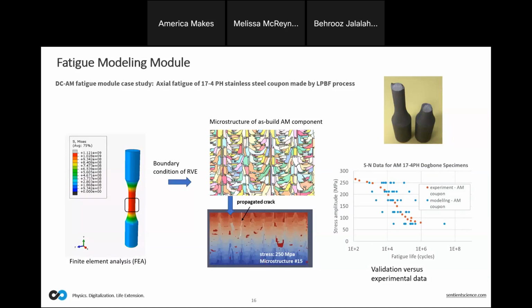As you can see, the prediction of the microstructure is in the middle, and then we put it under axial loading and get a range of fatigue lives. On the right-hand side, you can see the comparison of our prediction versus the experimental measurement that we did on the same sample. So we experimentally manufactured a few samples, put them under fatigue loading, and also did the simulation. As you can see, our prediction is wider than the experimental data.